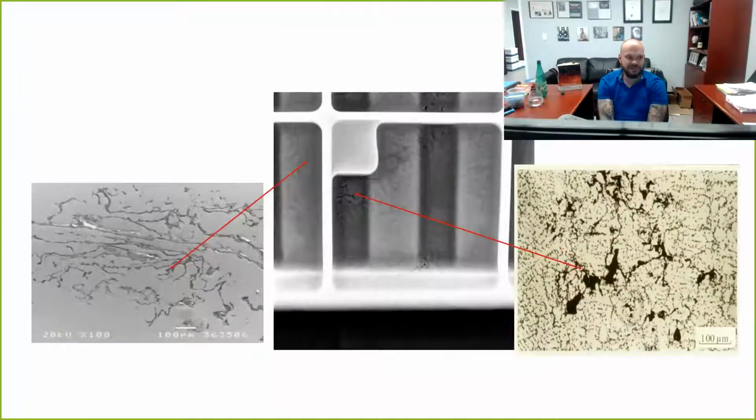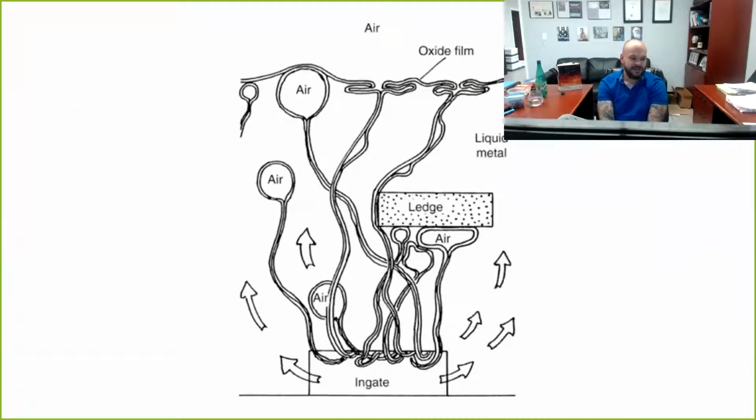And back to the original slide, on the left, you can see those compacted furled oxide films in the area that solidified quickly. And the area that solidified slowly, the oxide films start to open up. These are all the exact identical things that we're looking at here. All right, so that's the entrainment of the surface. I think we can understand that as clear as day. If anybody has any questions, butt in now.